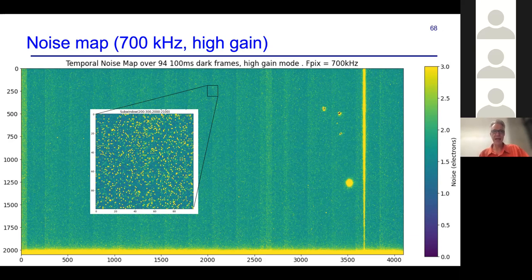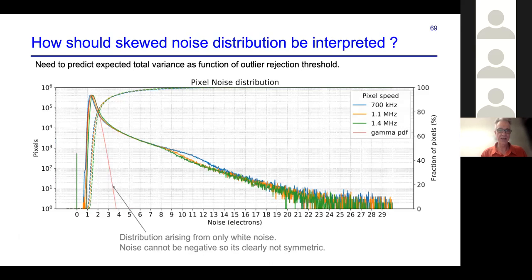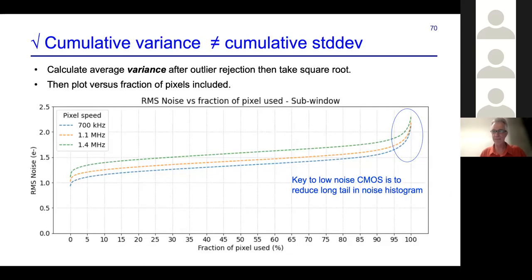Well, okay, this is somewhat intermediate result. You can see this is a map of the noise. Another important point is that with CMOS devices, every pixel has its own gain and offset and personality. And so we have to describe everything with histograms. And so here's a histogram of the noise distribution at different read rates. And a good way to look at this is not to look at the cumulative standard deviation. That's the wrong idea. What you've got to do is add variance, not add standard deviation, because it's noise.